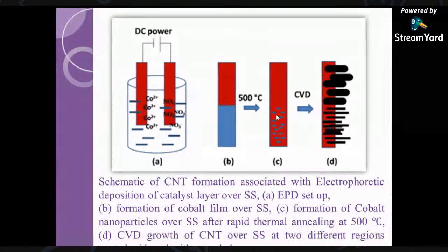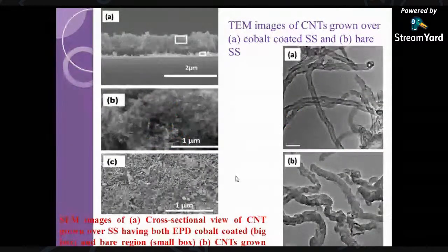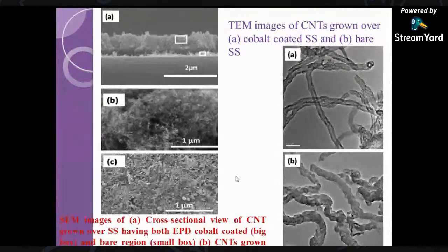And when we subject this to a chemical vapor deposition process, we can see the output with carbon nanotubes growing on this substrate. The beauty of this experiment is that you get two types of carbon nanotubes. One type of carbon nanotubes comes from these cobalt nanoparticles, and the other one is from the stainless steel, where you have bulk carbon nanotubes. Okay, so it was a very interesting piece of research for extracting the most crystalline carbon nanotubes. Here in this same picture, you can see the different morphologies of carbon nanotubes obtained using this technique.